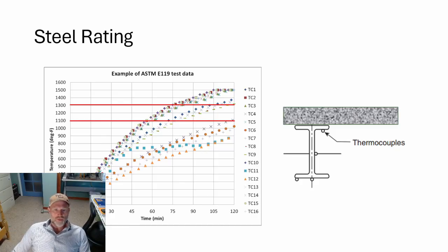So this particular chart shows a standard structural beam in fire conditions in the ASTM E119 standard fire furnace. Anytime you hear standard fire, the standard fire is the ASTM E119 model. What's interesting here is you have concrete on top of this I-beam, which models the typical application for structural steel: a beam with concrete on top. What's important to note is that in a fire condition, that concrete above the beam's flange is going to transfer energy. It's basically a heat sink. So you're going to have energy transferring from the steel into the concrete. What happens then is the lower flange is going to have hotter temperatures than the upper flange, and because of thermal expansion, the lower flange expands more than the upper flange. And that's what gives you a smiley face profile for beams.